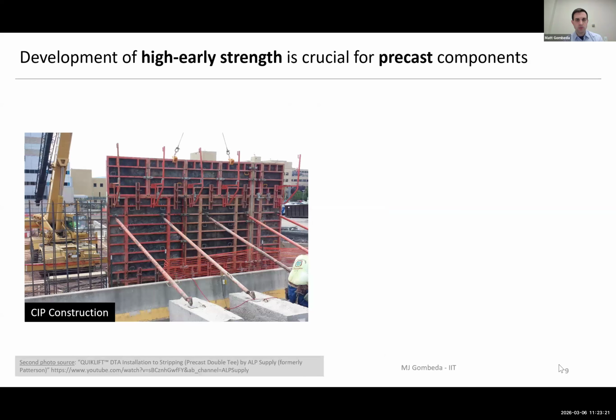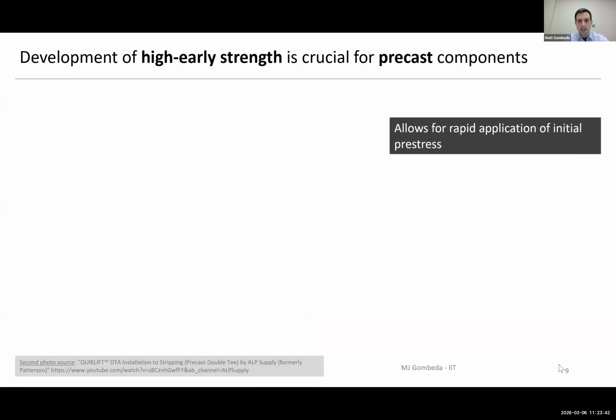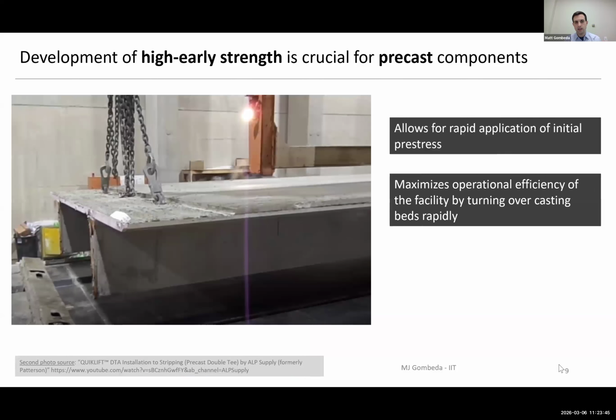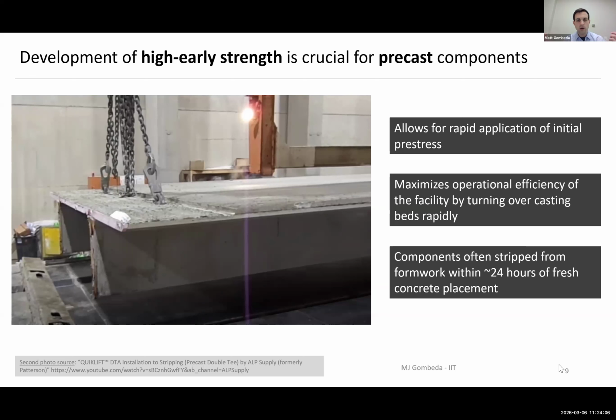And so now let's talk about the connection between high early age strength and precast. So in traditional cast in place construction, we see something like on the left where we have formwork and we have the concrete cast and it's in its final position. It never has to move and it never has to be lifted out of place. But versus if we're doing precast, we have to not only cast it in a bed and then lift it out, we have to do it very quickly. And the reason that we want to do it very quickly is because it's a business thing. It's an operational thing. The more precast components they can make out of a single casting bed, the more efficient from a financial perspective the business is. And we're talking about within 24 hours on most occasions, probably even less most of the time.